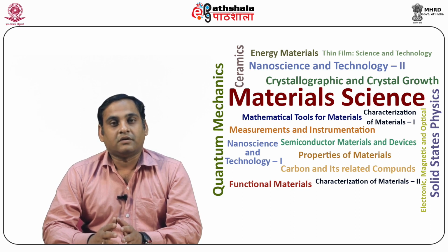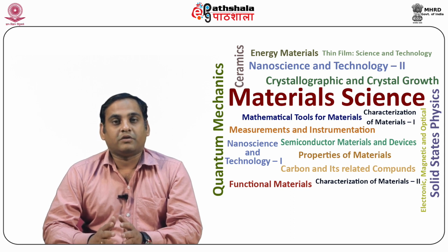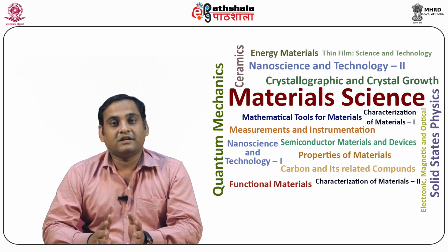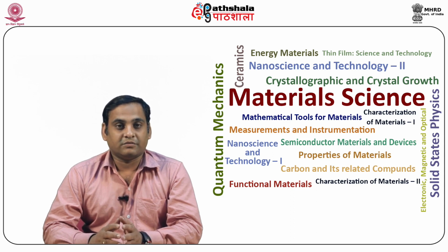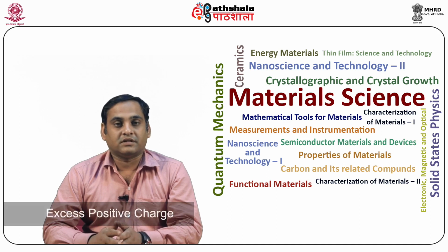For example, if manganese 4+ ions were incorporated on sites normally occupied by zinc 2+ in a zinc sulfide lattice, there may be localized levels associated with the Mn4+ ion, levels associated with the S2- and Zn2+ ions in the vicinity of the manganese 4+ ion, and levels associated with ions in the vicinity of a positive ion vacancy produced as a result of the presence of the Mn4+ ion to compensate for the excess positive charge.